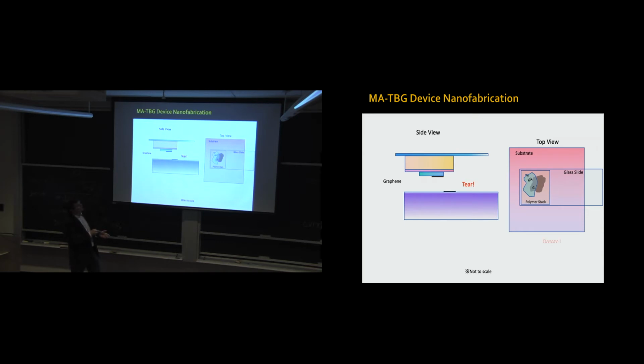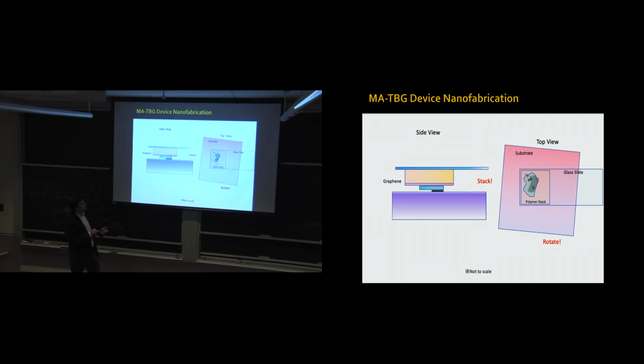So now I can rotate my substrate by any angle I want, say 1.1 degrees, why not. Then I shift it on top and stack it. Then I pick up the bottom graphene, and I have these two graphene sheets aligned with respect to each other at 1.1 degrees, pretty uniformly over a large area. Then I can continue to do nanofabrication of my devices.